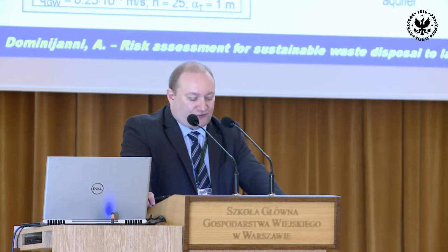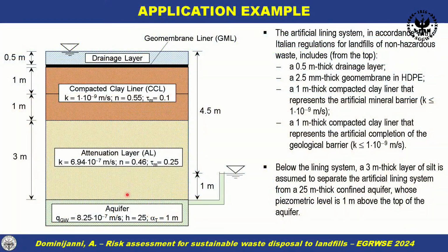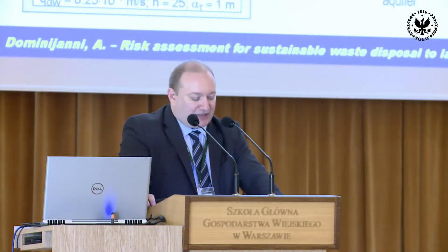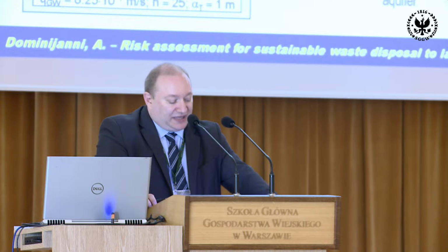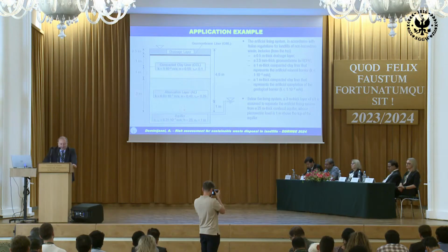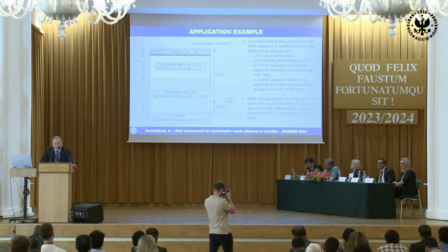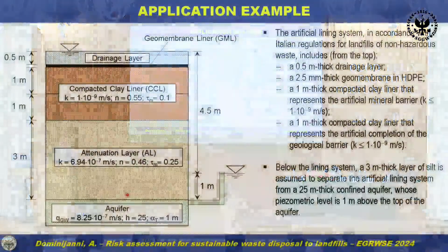The artificial lining system, in accordance with Italian regulations for landfills of non-hazardous waste, includes from the top a 0.5 meter thick drainage layer, a 2.5 millimeter thick geomembrane in HDPE, a 1 meter thick compacted clay liner, which represents, using the terminology of the European Directive 31 of 1999, the so-called artificial mineral barrier, and another 1 meter thick compacted clay liner that represents the so-called artificial completion of the geological barrier.